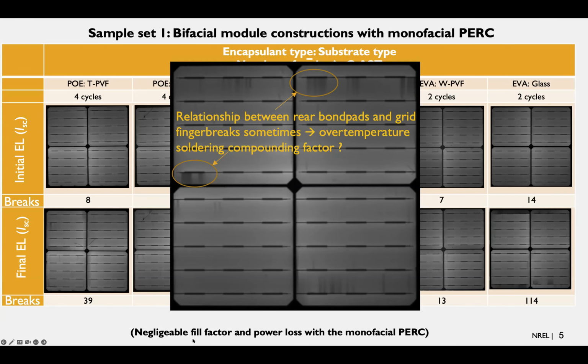That said, there was negligible fill factor and power loss in all of these samples. Despite the grid finger breakage, the extent of power loss was still fairly minimal. So it's something that could potentially develop further over time to lead to power loss, but to the extent we tested, the power loss, despite these important electroluminescent signatures, was rather minimal.